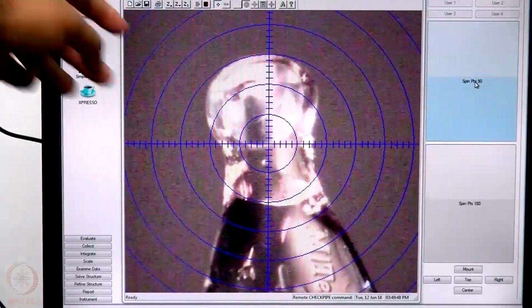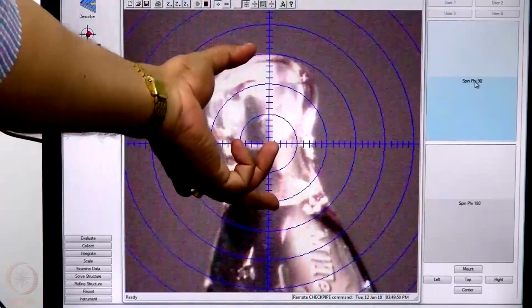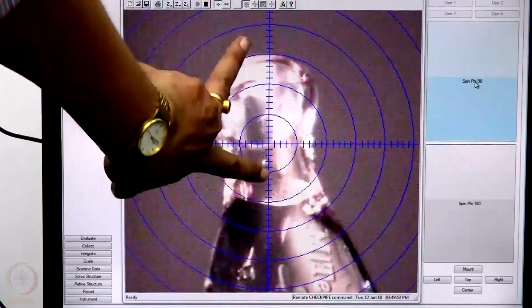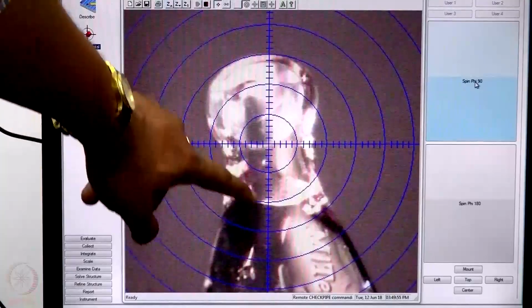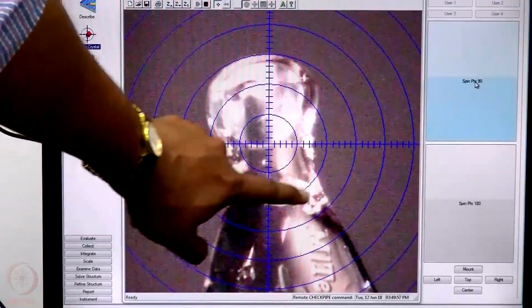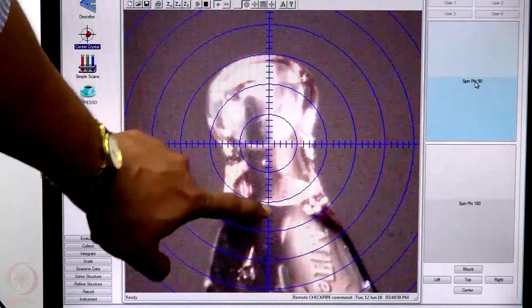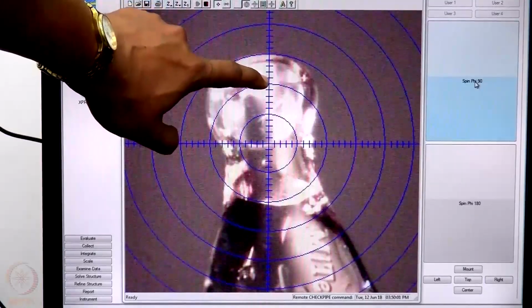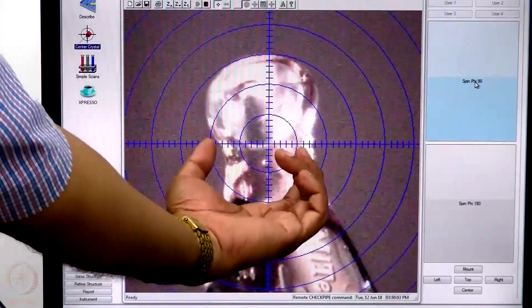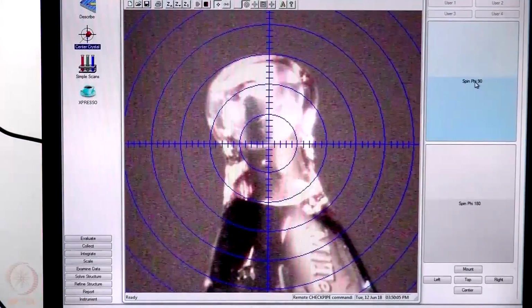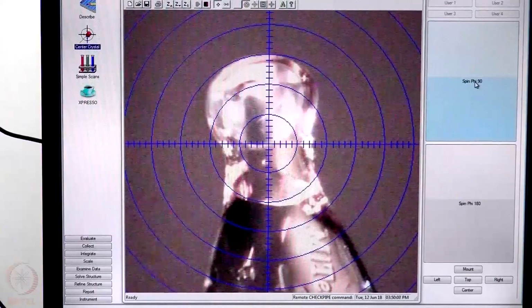So here you can see that the crystal is from here to there. So this is a reasonably big crystal. To get an idea, this particular ring is about 400 micron. So the crystal is about 450 micron in length and it is about 350 micron in width.